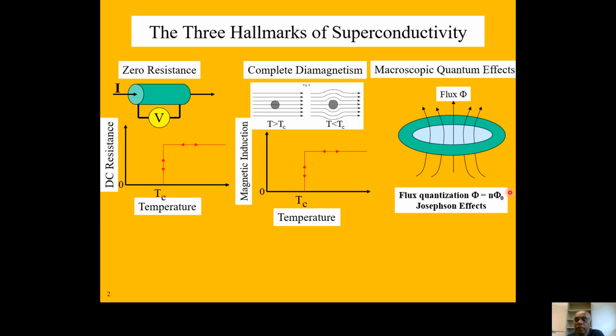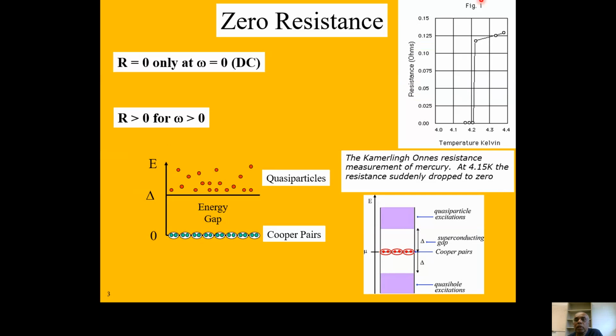So these are the 3 hallmarks of superconductivity. Actually this zero resistance thing was first observed, as shown in the right graph here, when Kamerlingh Onnes measured the resistance of mercury at 4.14 Kelvin, almost at the boiling point of liquid helium. He saw this finite resistance immediately going to 0 around that 4.15 Kelvin. So that's the first observation of this zero DC resistance.